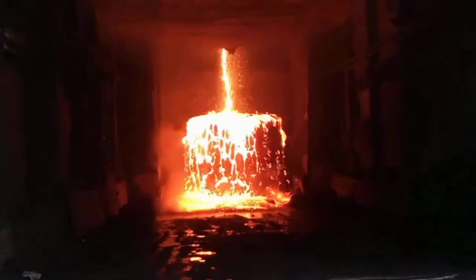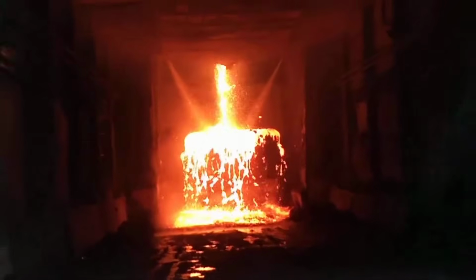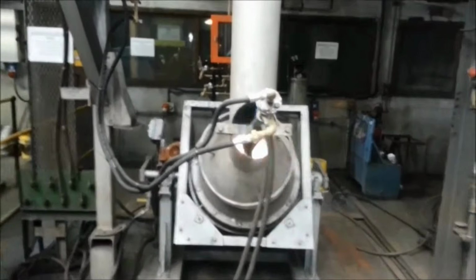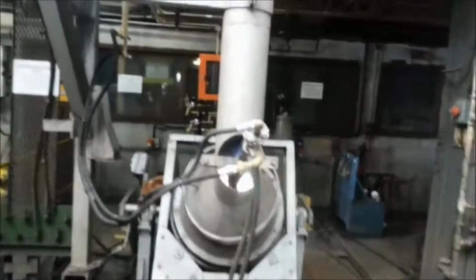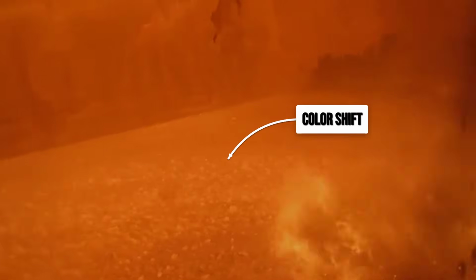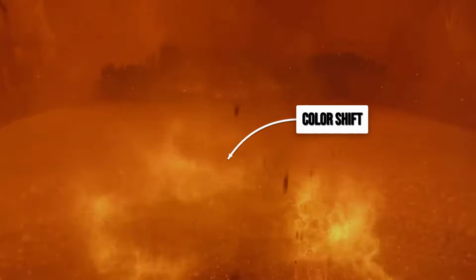Iron oxidizes first, captured by silica to form more slag. Then sulfur burns away as a choking gas. The superintendent, face shielded against the glare, watches as the matte's color shifts, a sign of rising purity.